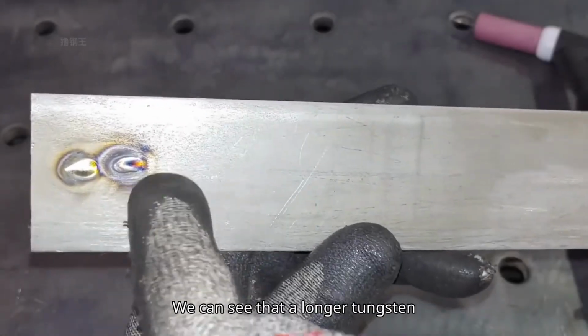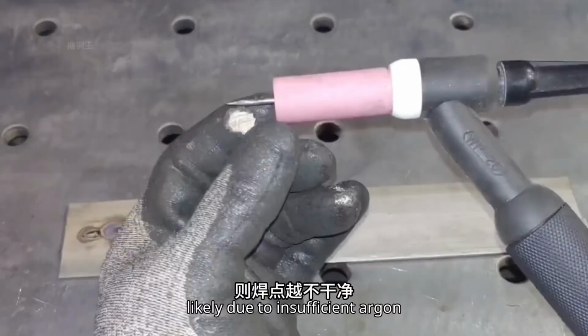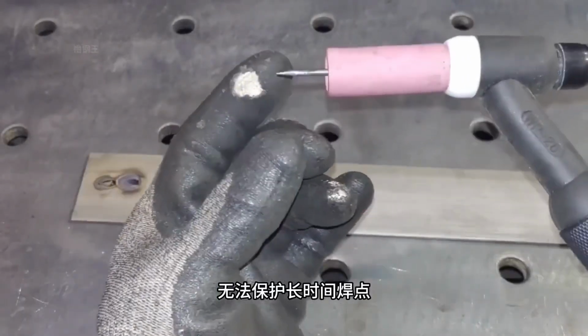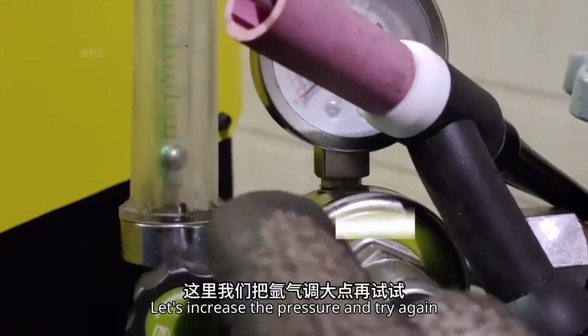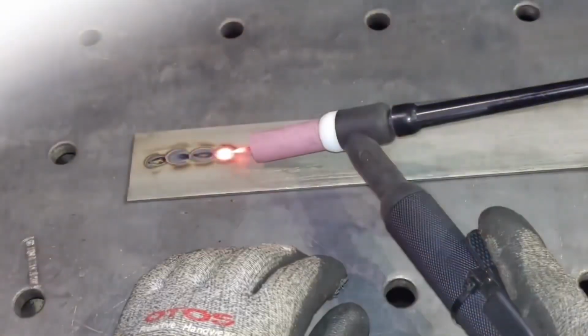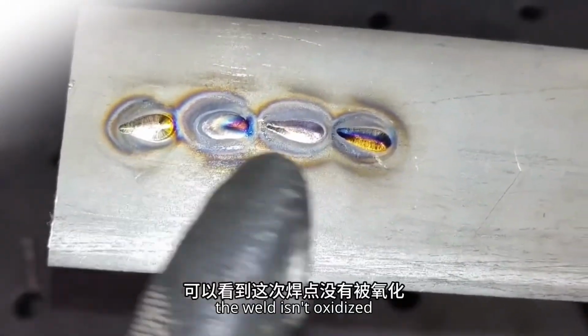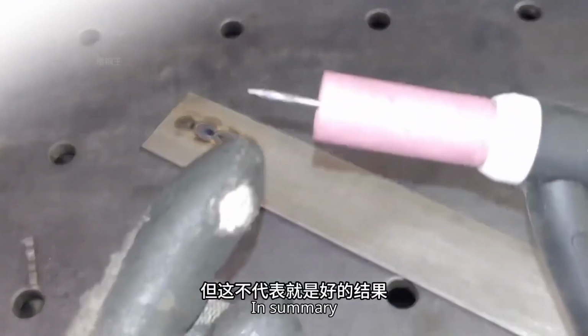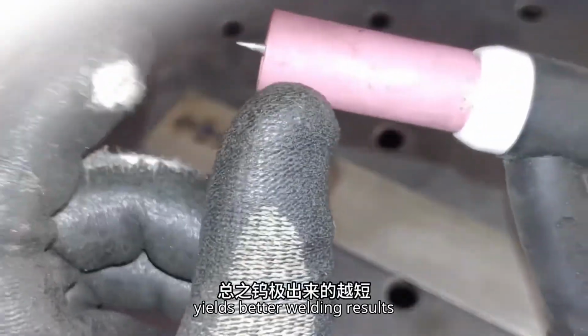We can see that a longer tungsten electrode leads to a dirtier weld, likely due to insufficient argon flow for prolonged protection. Let's increase the pressure and try again. This time, the weld isn't oxidized, but that doesn't mean it's a good result. In summary, a shorter tungsten electrode yields better welding results.